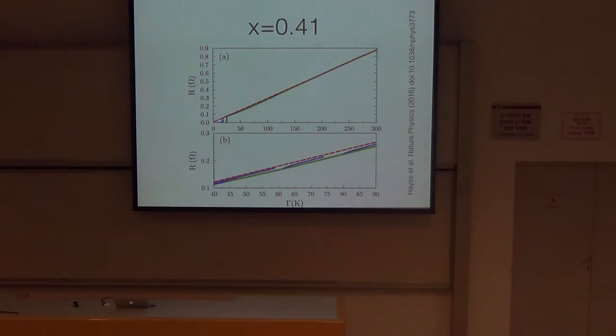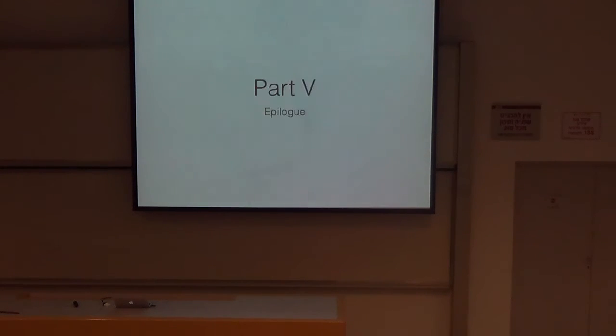But the point is that this was extraordinarily curious. All that we've done is the minimal analysis to achieve this. And this is really the minimal thing that you can do. Just replot the data as this new energy scale, and you see all of the curves tend to approach this T-linear line that we're familiar with from the zero field behavior.